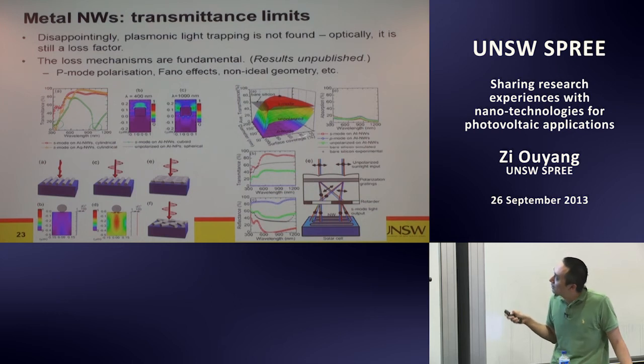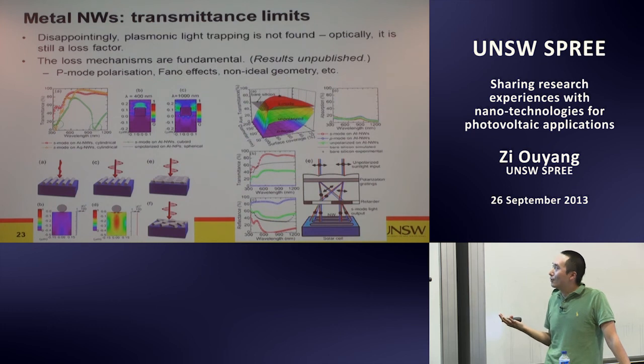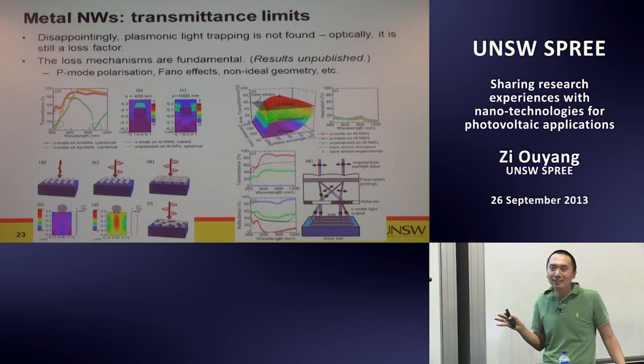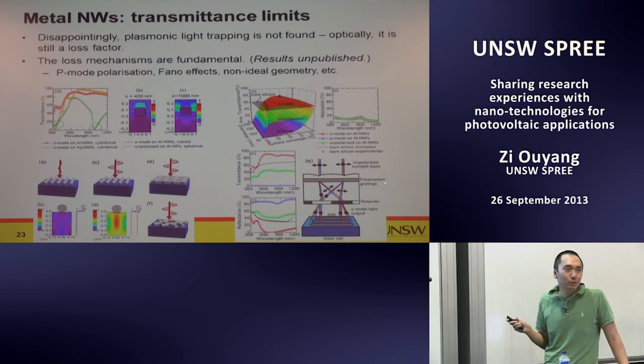So this is diameter and the surface coverage. There was one design that uses a polarization grating on top of the nanowires, so that with unpolarized light shining on the surface, you may only get the polarization you want. I think you won't realize this in the next 10 years, but that's if nanowire is going to work. Actually, a lot of people work on that. I doubt it, but if it's going to work, I think this is another key factor to realize it, because you just don't need to worry about the conductivity anymore.